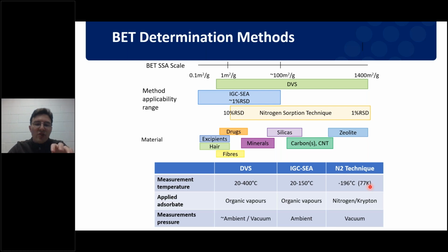First of all are the conditions that are required for this technique. The nitrogen adsorption technique relies on nitrogen being at a cold temperature, 77 degrees Kelvin, in order for this interaction to be a surface interaction. And it also requires vacuum drying prior to the nitrogen being introduced. Now, those harsh conditions, those low temperatures, those vacuum drying conditions, very well could cause a phase transition. They could cause the dehydration of a sample, and they could cause the collapse of some fragile crystal structures. That can cause you to change the surface area of your sample before you've even measured the surface area. So the methodology of this technique may not suit all materials.